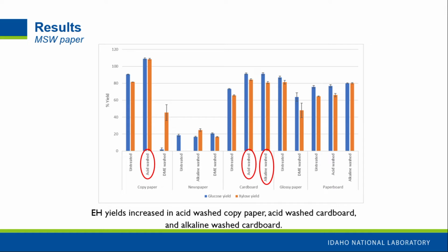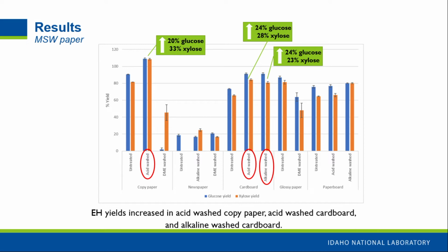But we did not really see much of an increase in yield except for in these three methods. For copy paper, our acid wash was able to increase glucose yield by 20% and xylose yield by 33%. And in cardboard, both acid wash and alkaline wash were able to increase our sugar yields. The interesting thing about the acid washing is that I told you before that, in our previous experiments, the copy paper had a really high pH. And so we think the phenomenon we're seeing here is basically that we're just neutralizing that high pH that we see in copy paper.